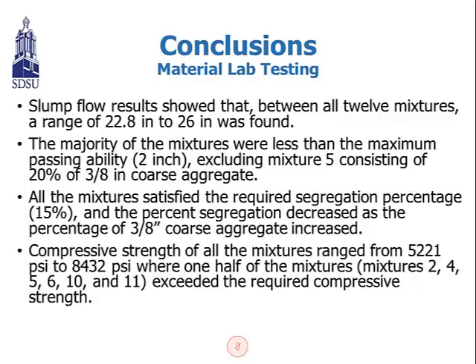The first, slump flow results showed that between all 12 mixtures, the range was 22.8 inches to 26 inches. And the majority of the mixtures were less than the maximum passing ability of 2 inches, excluding mixture 5 consisting of 20% 3/8 inch coarse aggregate. And the compressive strength of all mixtures ranged from over 5,000 to over 8,000 psi. And one half of the mixtures, mixtures 2, 4, 5, 6, 10, and 11, exceed the required compressive strengths.